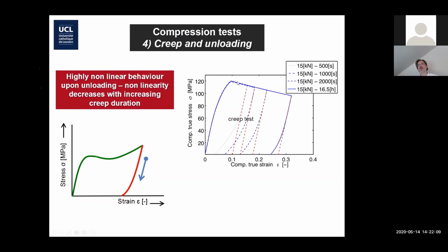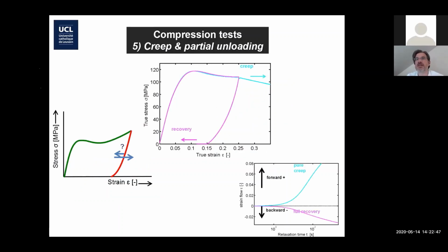Now we're gonna let it creep longer, and again unload, and look at the unloading curve. Immediately what you see is that the amount of nonlinearity upon unloading is much lower when you let it creep long. So it's like if by letting the material relax by creep, you do something, and we will explain that later, you let the material stabilize in such a way that during unloading you have less Bauschinger effect, if you want, which will be related later to backstress.